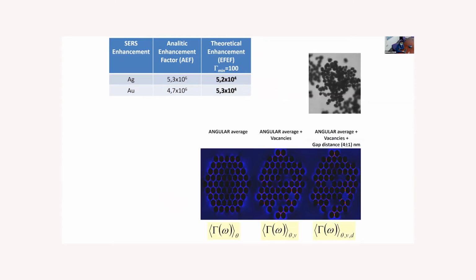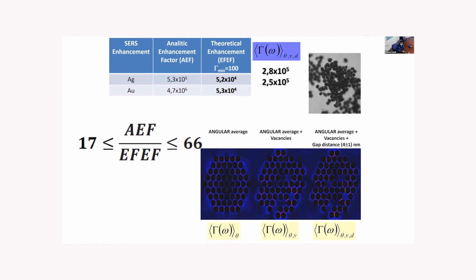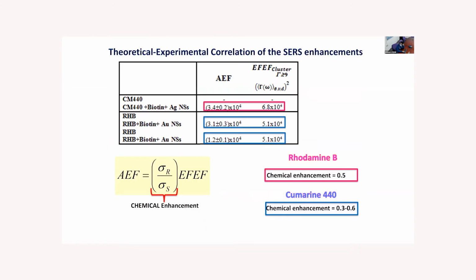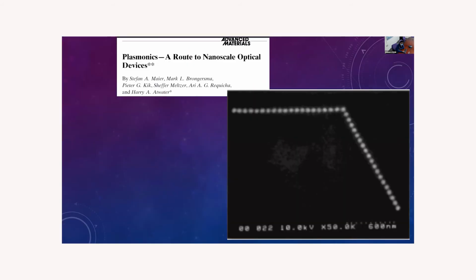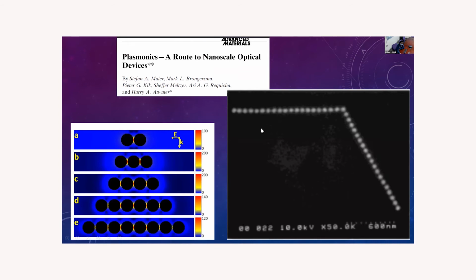Well, we try to emulate the natural vacancies that originate during the aggregation process. In that way, we reach something close to the analytic enhancement factor. But let's continue with this. In this case, we can say that this is a cluster, but a very ordered and linear one. And I did some calculations, not for this, but it can be useful.